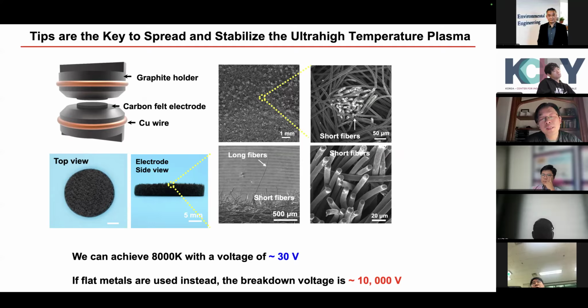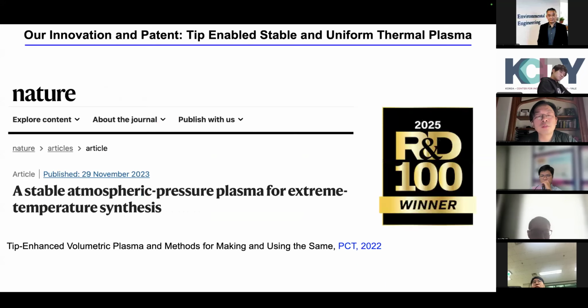And it's striking here that the voltage for achieving the 8,000 degrees C plasma is only about 30 volts. So the voltage is really, really small compared to otherwise, using metal plates, you would need thousands of volts to achieve that kind of plasma. That means you can turn this plasma on and off, and you don't have to have special machines, and you can achieve this plasma in almost like a portable system, right? I think this is really important not only for material discovery, but also for manufacturing, especially if you have a distributed system.